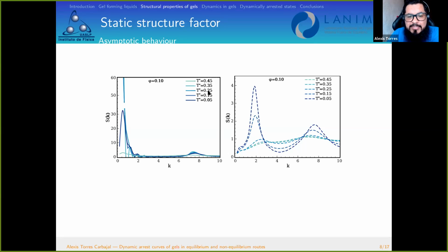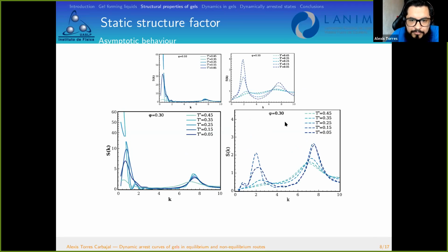But we can observe in this scenario that, depending on the thermodynamic states, the static structure factor exhibits a peak. For example, in the case of the Lennard-Jones fluid, this first peak tends to diverge, indicating a full phase separation in the system. But in the case of the Lennard-Jones with Yukawa tail, we cannot observe this behavior. So this is the main feature that distinguishes the respective non-equilibrium route and equilibrium route.